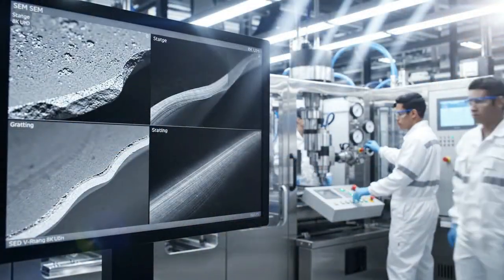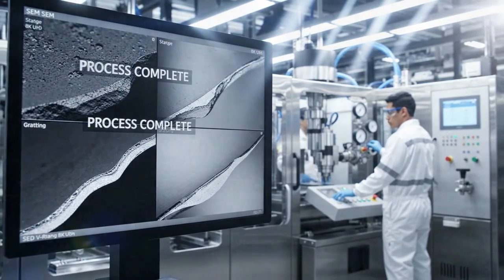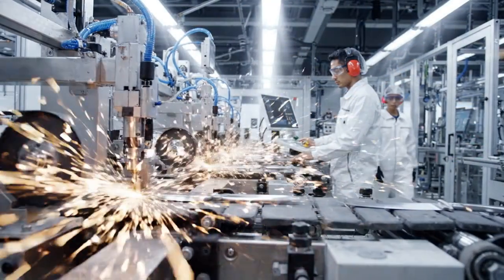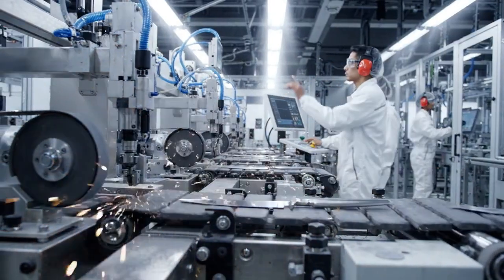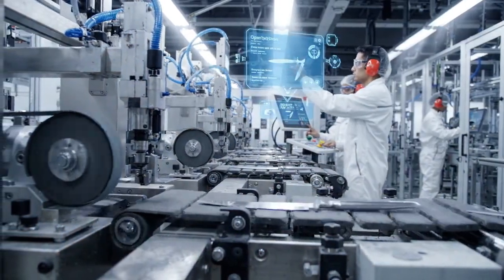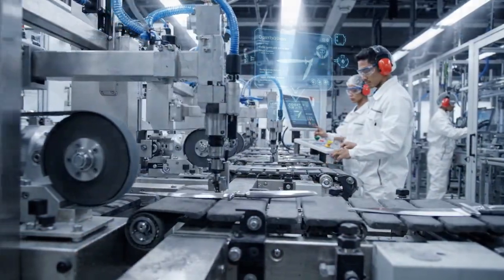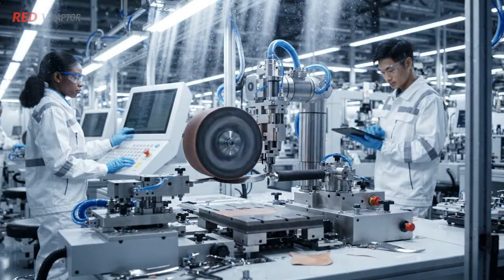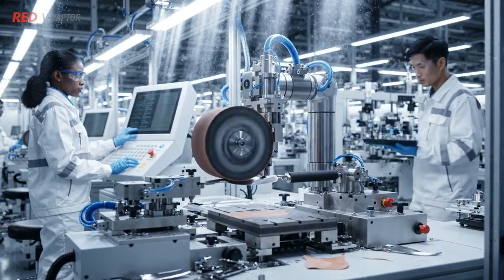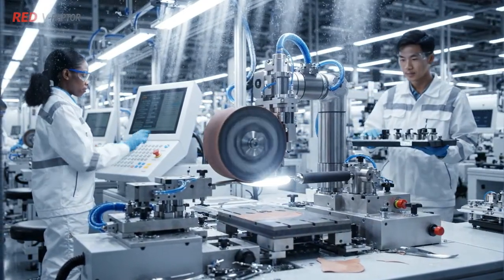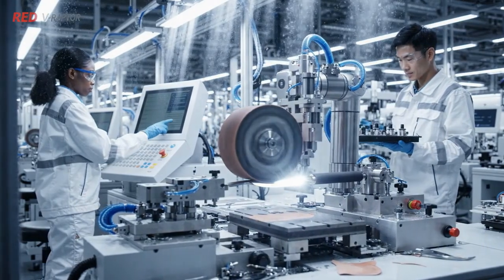Edge formation requires 3 to 5 progressive grinding stages, each using finer abrasive to refine the edge geometry to the final cutting specification. Each grinding stage removes less material than the previous one, with the final stropping stage removing material measured in single-digit nanometers. The final stropping stage produces an edge apex radius smaller than 100 nanometers, less than 1,000th the thickness of a human hair.